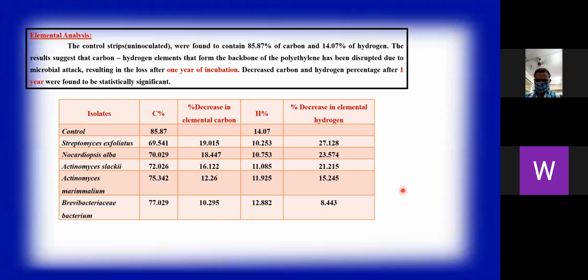Next, coming to the elemental analysis, the control strips were found to contain 85.87% of carbon and 14.07% of hydrogen. Whereas after 1 year of incubation, the carbon in Streptomyces exfoliatus has changed from 69.54 to 19.01, followed by Nocardiopsis 70 and 18, and they have gradually decreased and been arranged in a decreasing order: slackii, marimmalium, and Brevibacteriaceae bacterium.